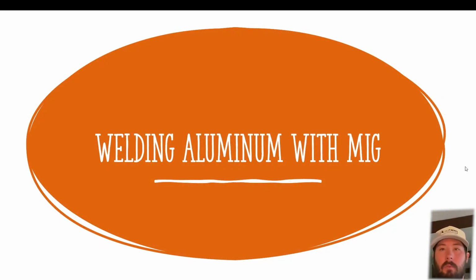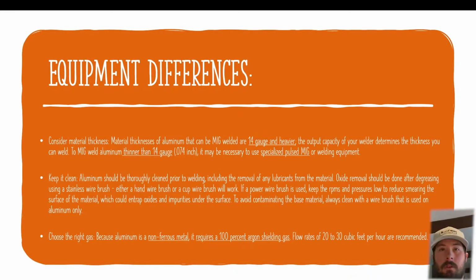So next we have welding aluminum with MIG. So a few equipment differences when using MIG on aluminum. You have to consider the thickness. It's usually best to weld on a 14 gauge or heavier aluminum. If you're gonna weld on thinner than 14 gauge, you'll probably have to use specialized pulse settings.